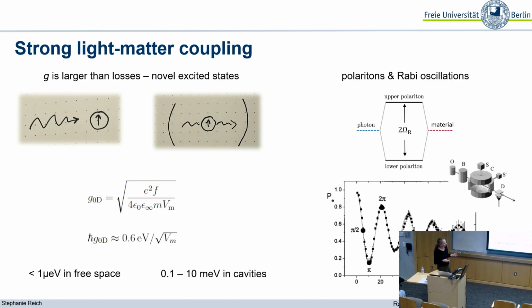Instead of having really a separated photon and material excitation, the two of them start to interact and build a hybridized state. So instead of having the photon and the dipole in resonance, they will hybridize and you will get a lower polariton and an upper polariton, and the energetic separation between the two is known as the Rabi splitting, and it corresponds to twice the interaction strength for light-matter coupling in your system.